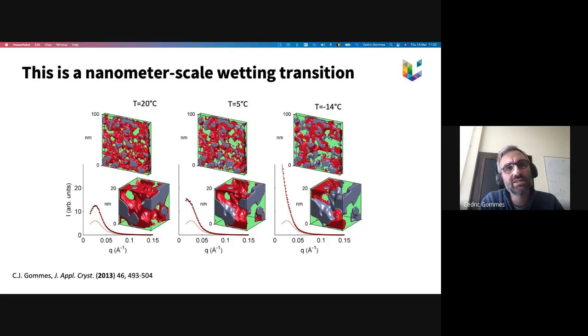And what you're seeing actually is that it's a de-wetting transition. So basically, at high temperature, the nitrobenzene makes a nanometer thin layer that covers the surface more or less homogeneously. And when you're cooling it down below the critical temperature, you have these de-wetting transitions. So you see these bare patches of the solid that appear, and the liquid gathers into these plugs there. What's happening there actually is that when you're moving away from the critical point, the surface energy of the hexane-nitrobenzene interface increases, and this is what is driving this process here.